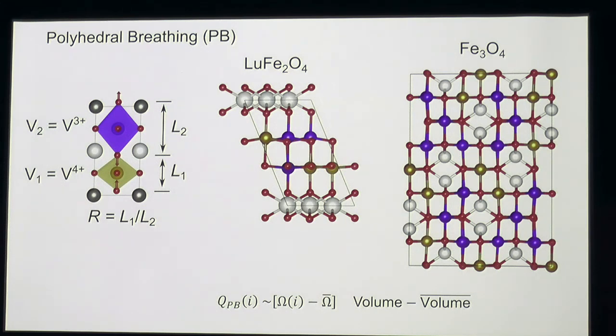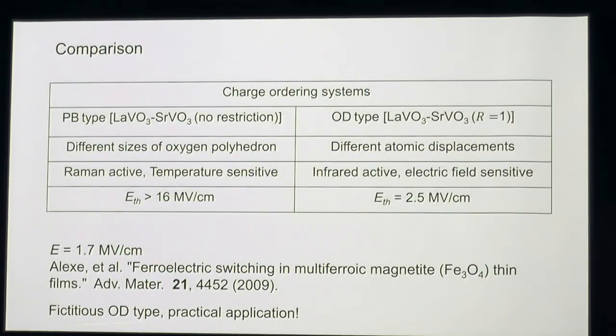Sorry if you said this, but what's the space group for the magnetite case? Sorry, I couldn't memorize exactly. It should be something around Cc, space group 9. Okay, and the switching fields you talked about, they seem big to me. Are they within the range before there's dielectric breakdown in these systems? The fields you mentioned, over 2 megavolts per centimeter? Yeah. Are those within what you can support in these materials before they break down? I think so, because in previous experiments, they mentioned that the value for flipping the polarization is 1.7 megavolts per centimeter. Maybe a little different, but in the same order of magnitude with the value in our study.